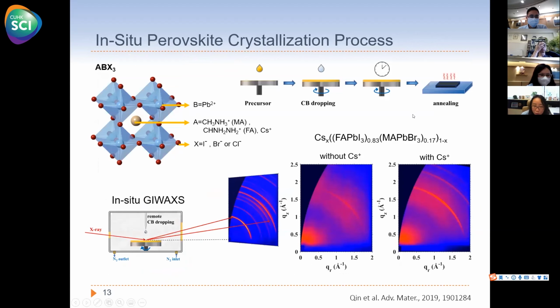The last example I want to show is how we can use in situ GIWAXS to understand the perovskite crystallization pathway. The perovskite solar cell is another type of solar cell which is very hot recently because the efficiency is above 25%. The structure is well defined, much more well defined than the organic solar cell. Basically, lead halide octahedra share corners to form a cubic structure, and then we insert a large cation into this cage to stabilize the cubic structure. But if the size of the A-site cation is too small or too large, the cubic structure will collapse.